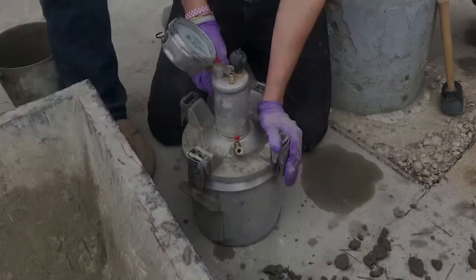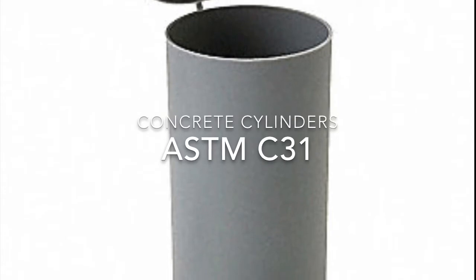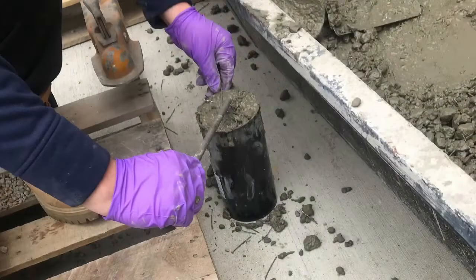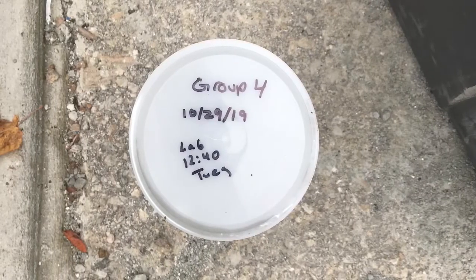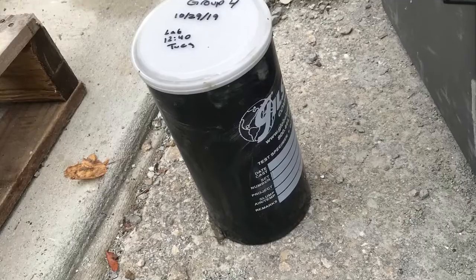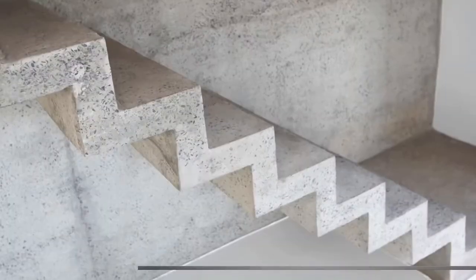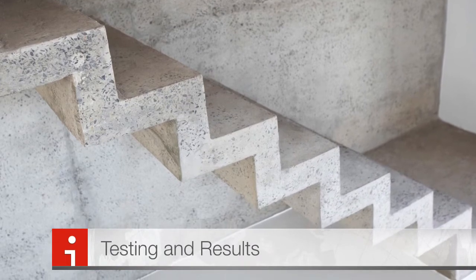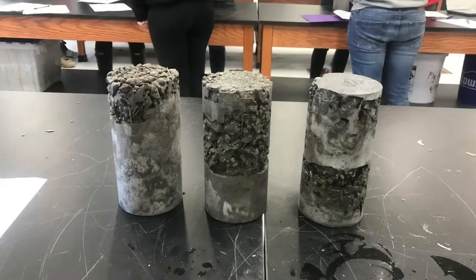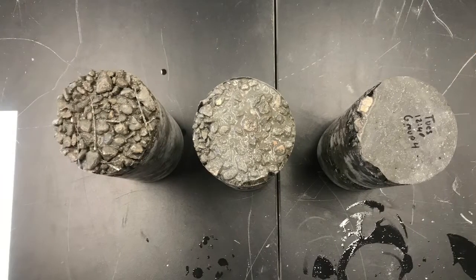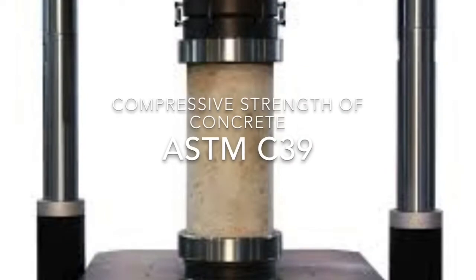The last test for our concrete mix was to fill 3 cylinders using ASTM test C31. After filling the 3 cylinders, they were left to set and later cure for 7 days before performing our compression test. Before testing, the cylinders had noticeable segregation and large pore spaces within the cylinder, thus making it prone to failure. As noted before, more cementitious material and equivalent water could have aided in preventing this. To test the concrete strength, compression test ASTM C39 was used.